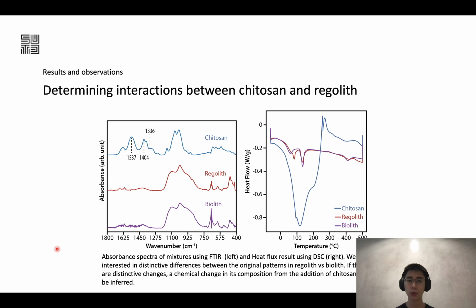Now, looking at these two graphs, the one on the left, which is the FTIR, and the graph on the right, which is the DSC, we actually can observe that there is no distinctive change in the spectra between the Biolith components, which is regolith and chitosan, and the end product, which is Biolith. And this led us to infer that there's actually no conclusive evidence that there is a chemical reaction happening between the components. Now, this means that the agglomeration is merely a physical interaction.